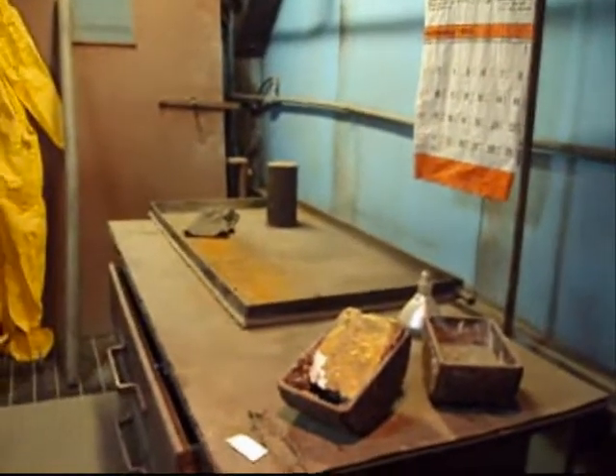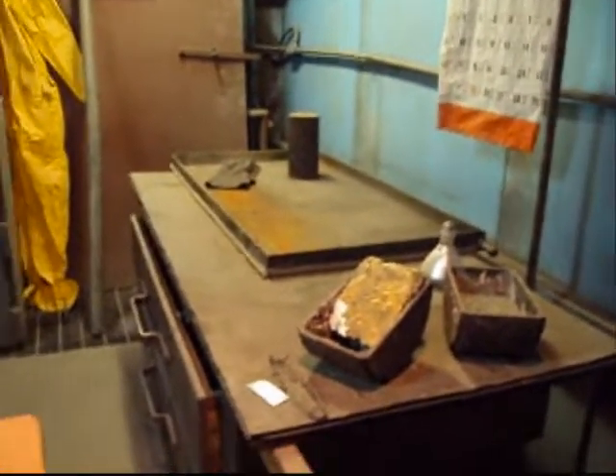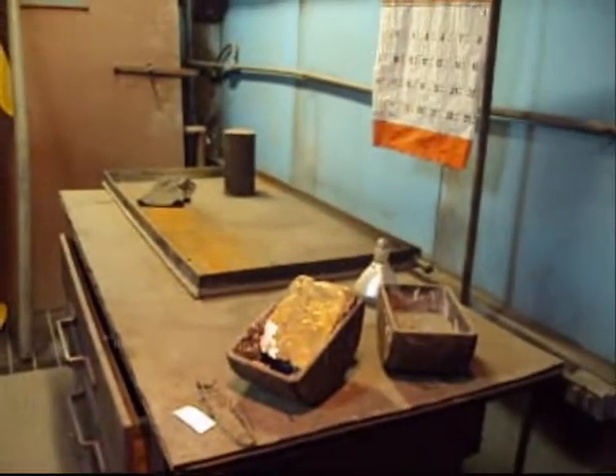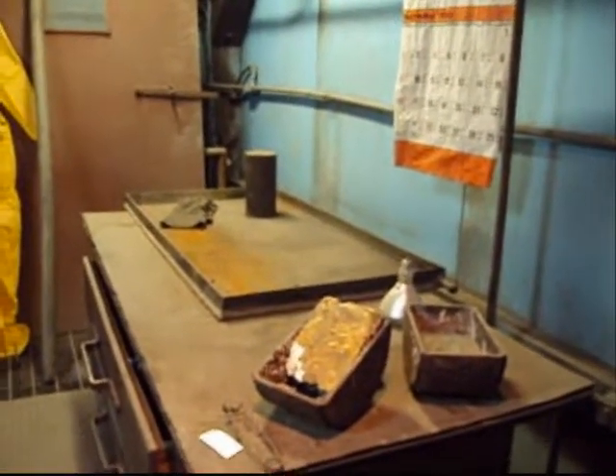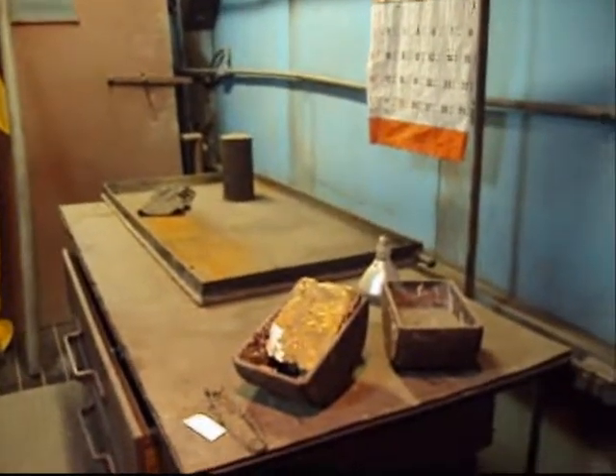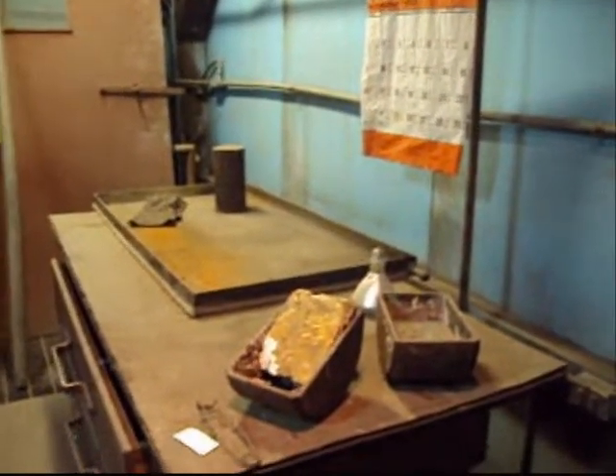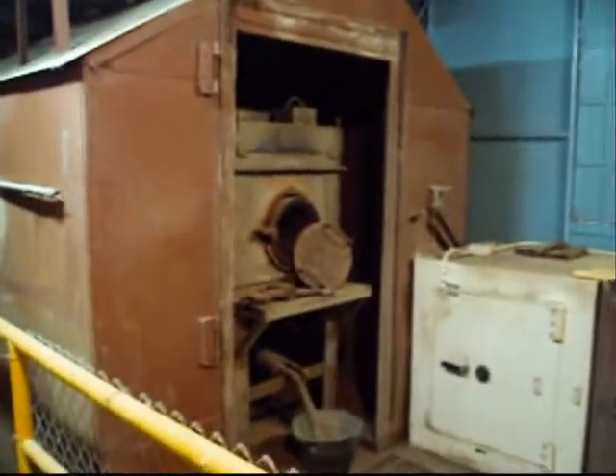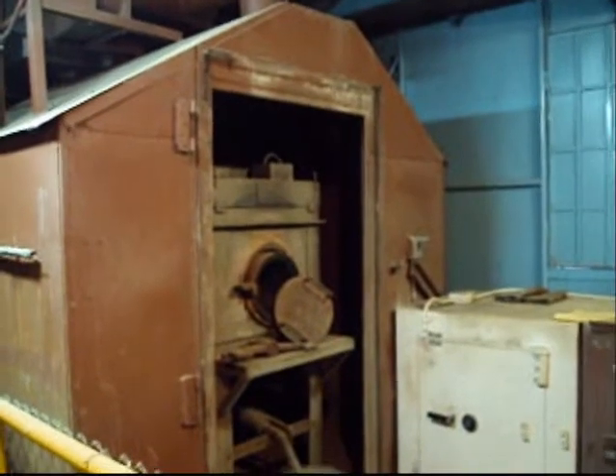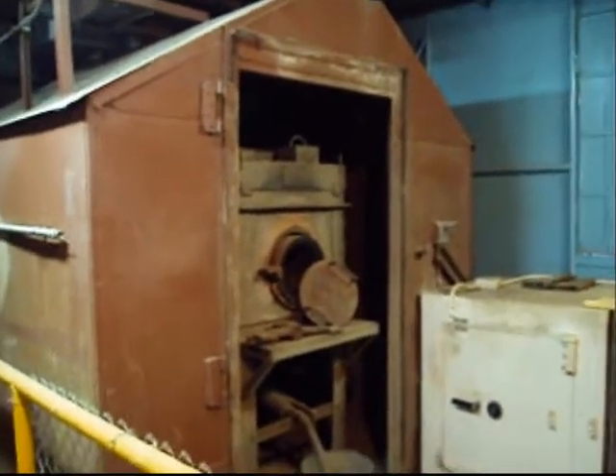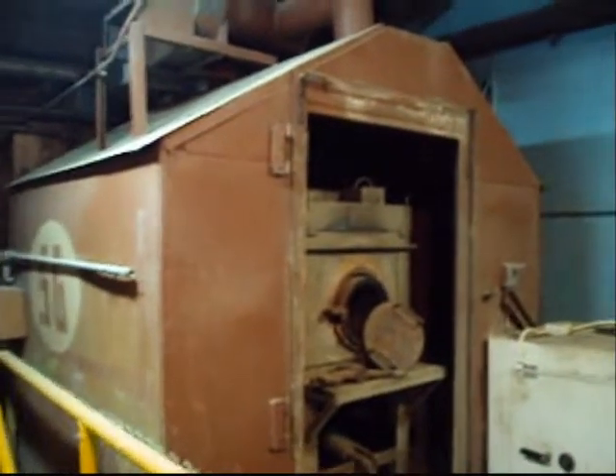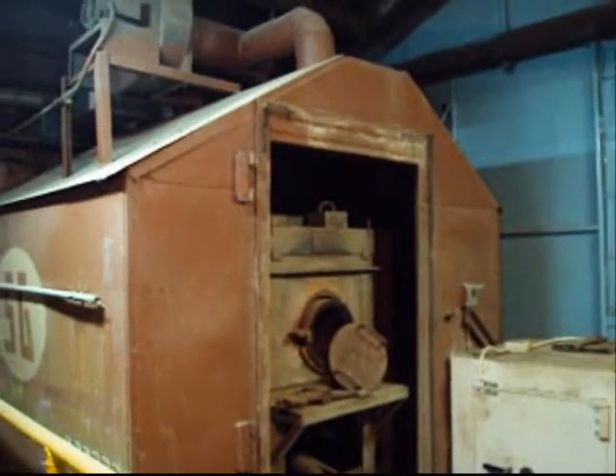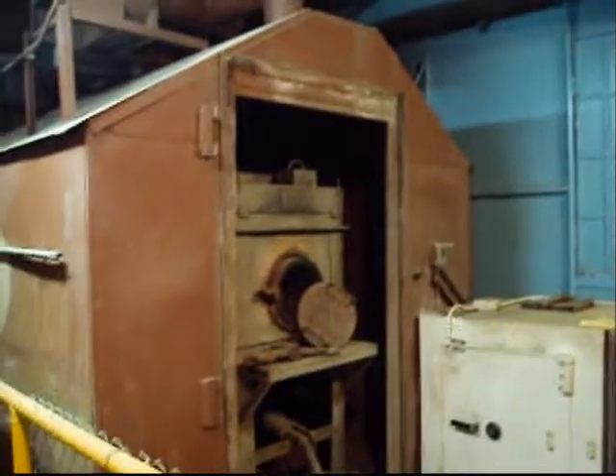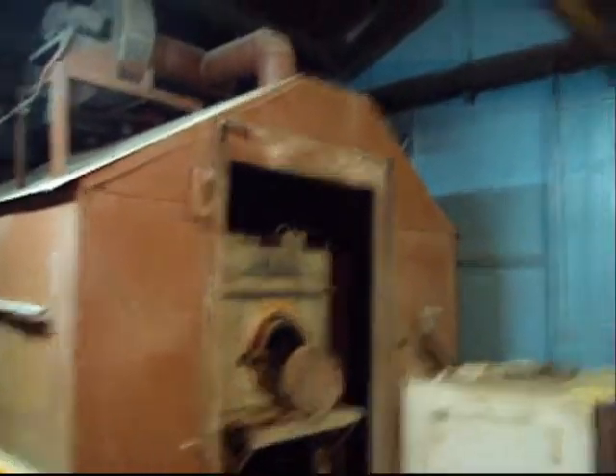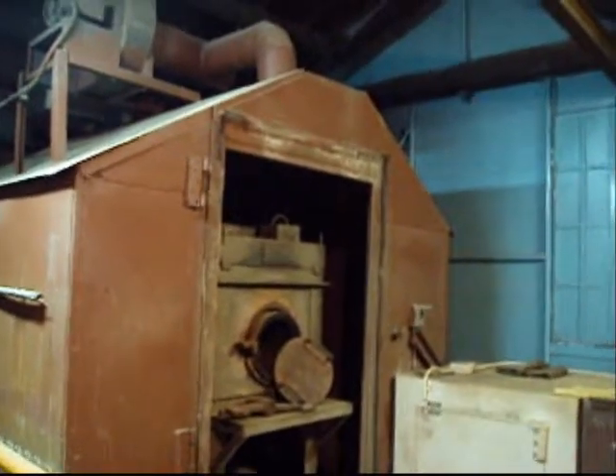Here is the retort, the last of the 5 steps in refining the metal. So you would take the amalgam cakes, as you can see there, and they were broken down into small pieces and placed in those steel half-moon vessels called boats. And then they were put into the retort oven and fired for 12 hours at 1200 degrees Fahrenheit to completely drive the mercury off. And then it would be turned off and allowed to cool for another 12 hours. The product of this was called a sponge. It was about 70 to 90% gold, with the remainder mostly silver and some copper.